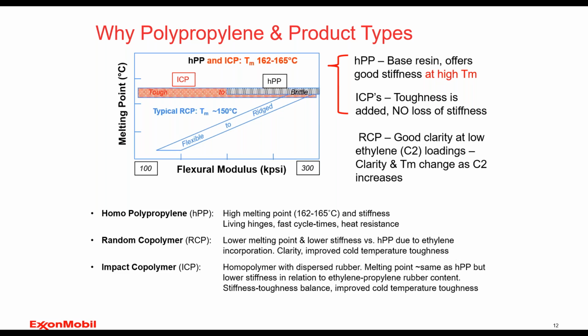In talking about the foundation of really the heat aspect, the high heat resistance, if we look up into the chart, we see the gray bar, which represents homopolymer, and it tends to be up to the higher stiffness end of the flex modulus, but it tends to be brittle. So the beauty of polypropylene is then you can take that homopolymer that may be deficient for some applications and toughen it up by adding some modifier, in this case an EPR rubber, and change that level of ductility response. You're also changing the flex modulus, so the flex modulus is going to move accordingly. But the heat resistance stays the same because that polypropylene matrix is spread throughout. That is ultimately what controls when the resin will melt.